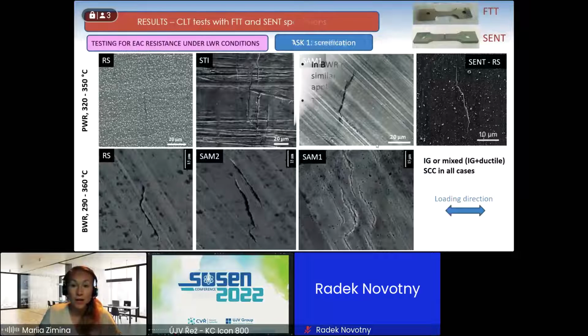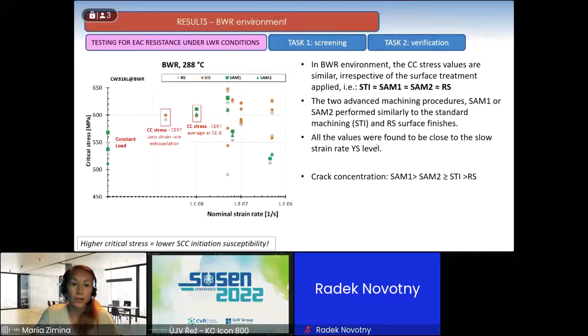However, if we look at the BWR environment, which is oxidizing environment at 288 centigrade, we can see that these calculated critical stress values are similar for all surface treatments, and with those two advanced machining procedures which were proposed, they perform similar to the standard machining used in the power plants and the reference surface finishes.